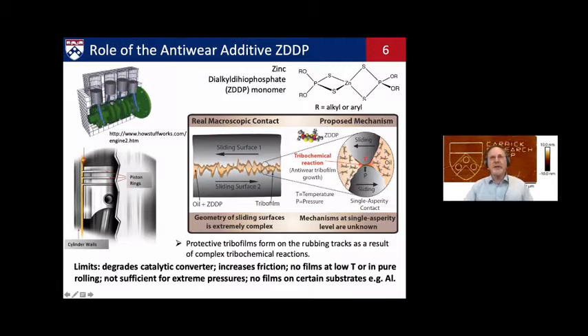You need some shear. And if you have stresses that are too high, too extreme, the films don't stand up to that. And as well, they don't form as well on certain substrates as they do on steel, like aluminum, lightweight aluminum-based alloys. So that means that we would like to reduce or replace ZDDP by finding alternatives. And to do that, a good place to start is to understand better how ZDDP works.